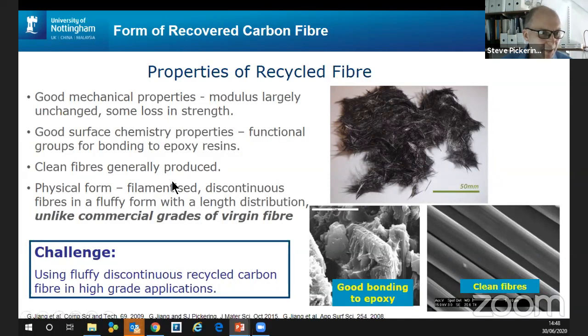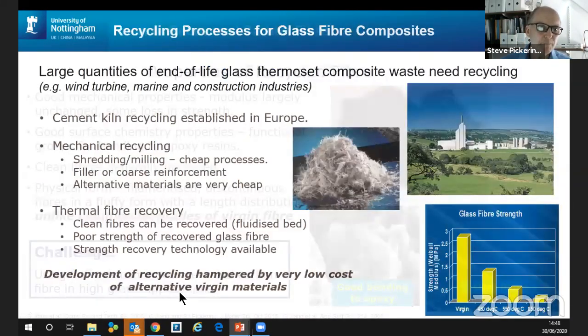We're producing clean fibers, but the physical form is filamentized, discontinuous fibers in a fluffy form, and here's a typical picture of the sort of fiber you produce, and they will have a length distribution. They'll not be all of one length, and that's unlike any commercial grade of virgin fiber. And so there's a need to think how those can be reused to get the best out of the recovered carbon fiber. So this is one of the key challenges. It's not just in recovering the fiber, but thinking how we can reuse it.